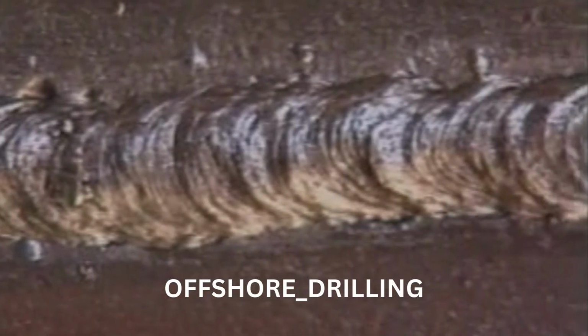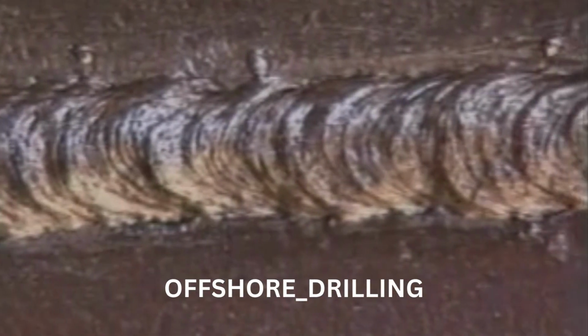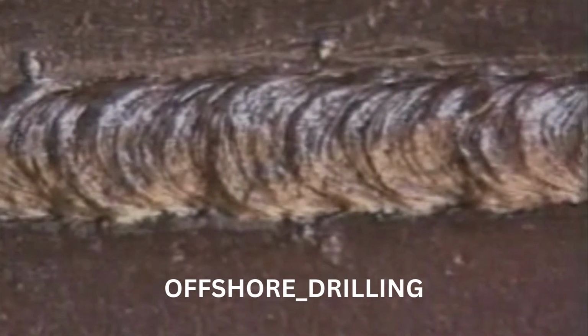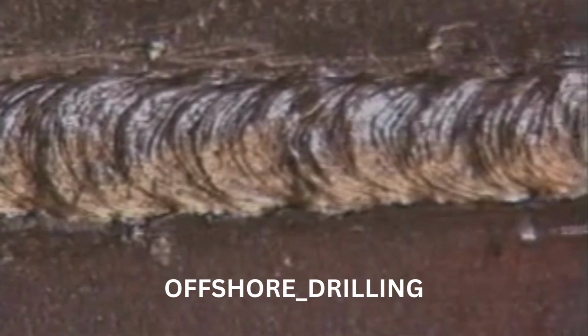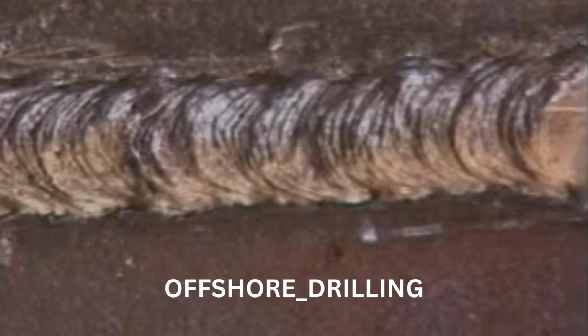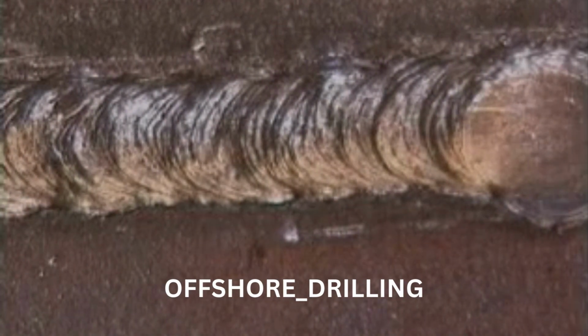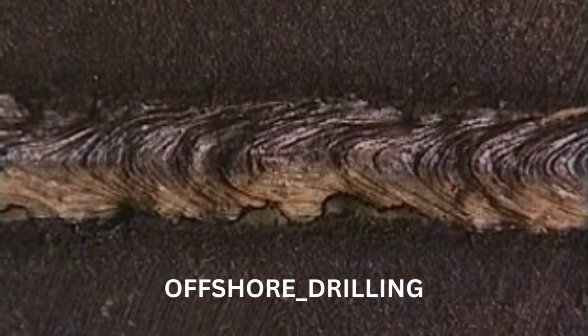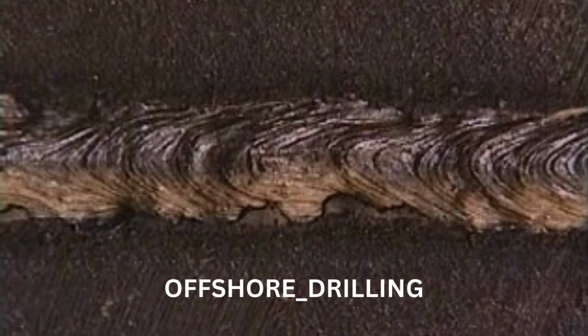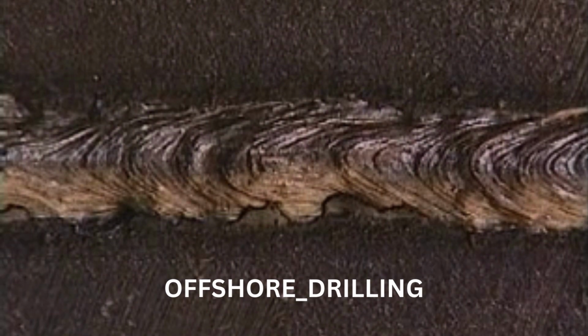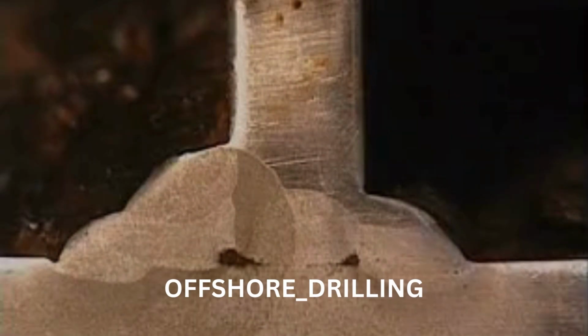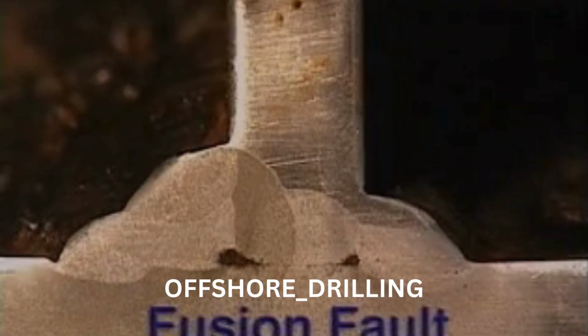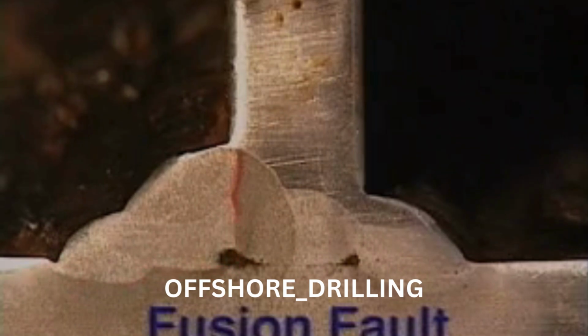A good weld will have evenly spaced beads of a regular, curved shape. It should be a consistent width with straight edges and a slightly convex profile. A narrow bead with a pointed shape indicates that either the travel speed or the electric current was too high. Moving the torch too quickly will not preheat the base metal enough for proper fusion with the filler material to occur. This means that the metals have not melted together and seriously affects the strength of the joint.